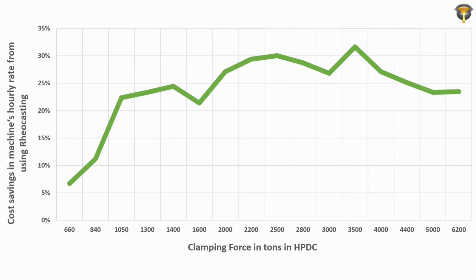That seems really too good to be true, but as you see in these examples, it's actually true, and we've seen it for so many other applications where, for example, because of porosity issues, you have an oversized die casting machine, and then with the same machine size you do a two-cavity tool of the same part in Rheocasting, because you can reduce the projected area, and then you have double the efficiency. That also has a massive impact on your hourly rate, as we see here, as you can usually reduce the machine size by 20 to 30%. When you compare the smaller machine plus the investment in the slurry maker, for the smaller machine the hourly rate difference is not that big, because in relation to the machine price, a slurry maker is relatively expensive. But in the middle segment or with large tonnage machines, the investment in the slurry maker doesn't really fall into account.